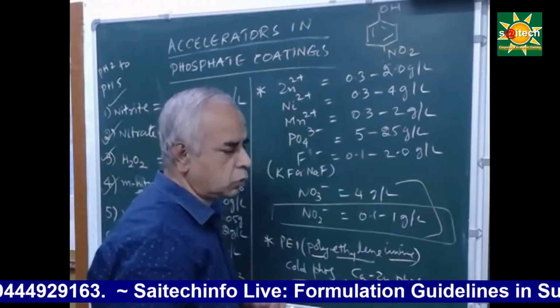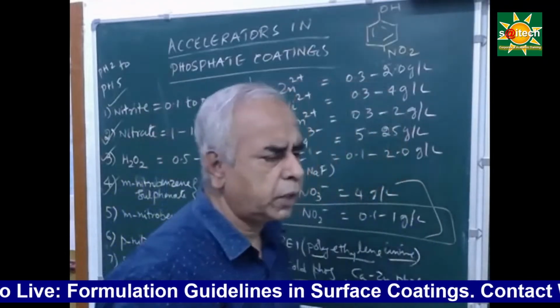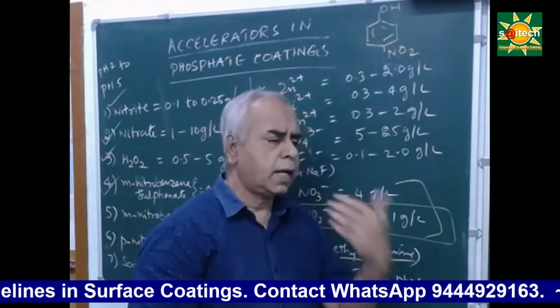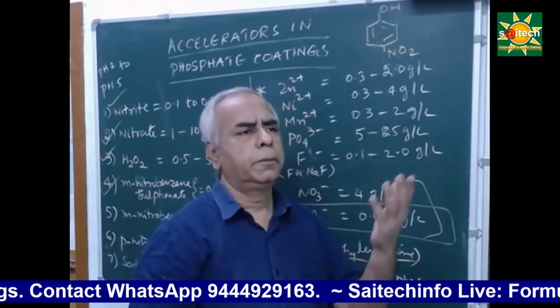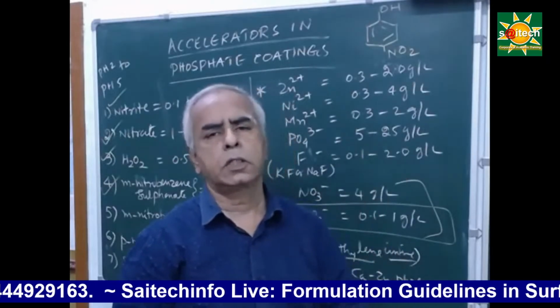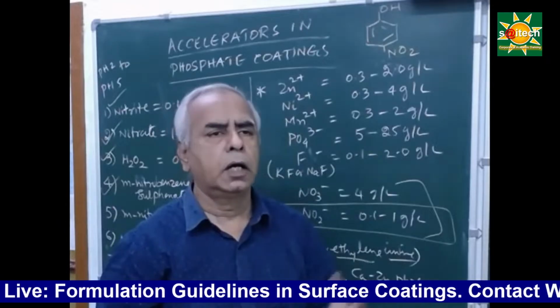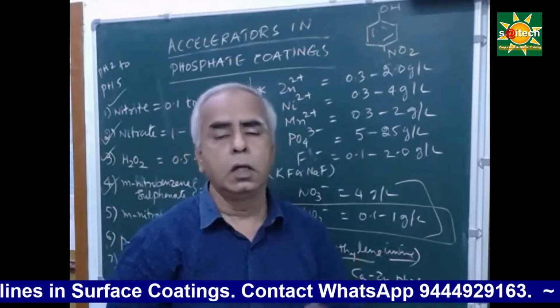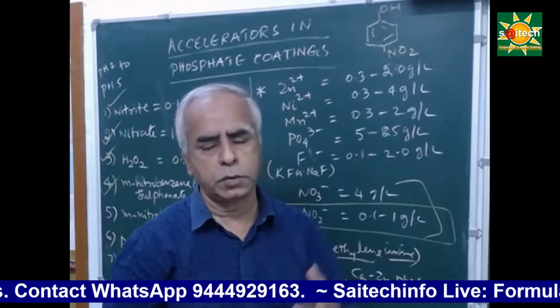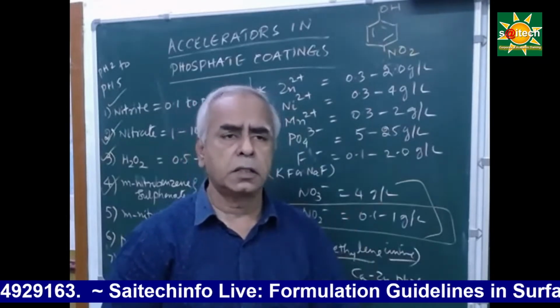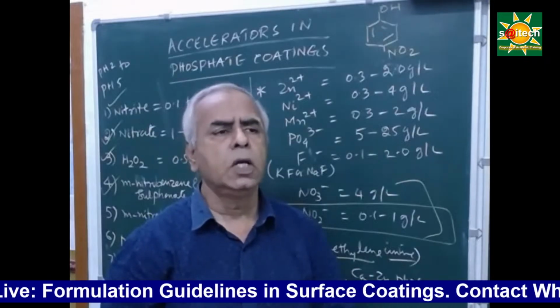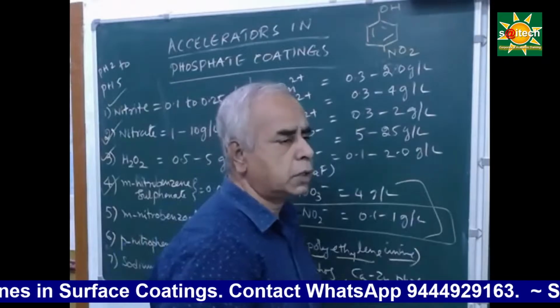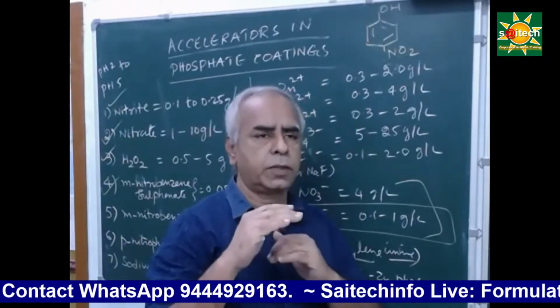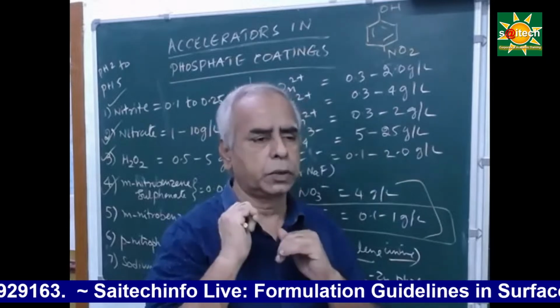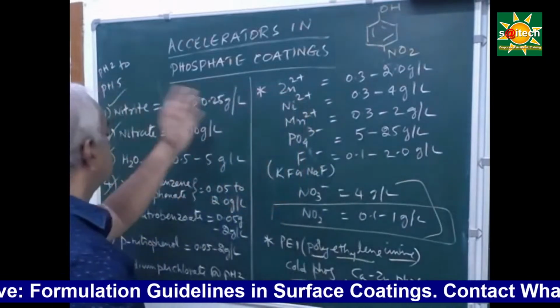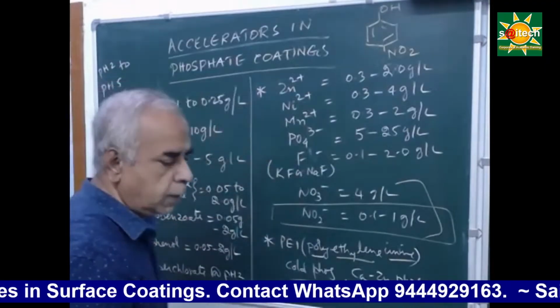There are 3-pack solutions also available that give very aggressive phosphating. It all depends on your requirement, and that phosphate requirement is based on your customer's requirement in terms of salt spray. For example, some people may insist on 200 hours, 240 hours, 400 hours, 600 hours, and in certain cases even 1000 hours of salt spray. So depending on the salt spray requirement, you have to choose the suitable phosphate system and also the top coat. I hope I have covered the very important aspects about phosphating.